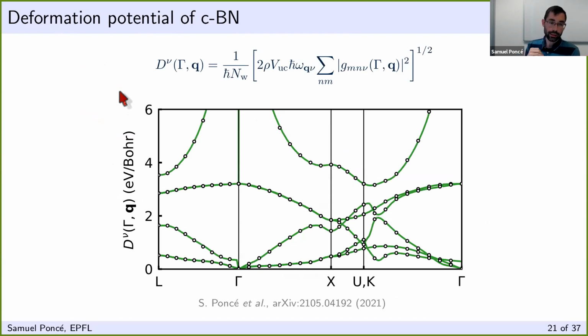So now we can look at the electron-phonon matrix elements, or more precisely, we can look at the deformation potential, which is the matrix element multiplied by the phonon frequency. Here I'm showing the deformation potential of cubic boron nitride. I'm showing this at k equal to the gamma point along the q high-symmetry lines, and I'm showing that for all the phonon modes of cubic boron nitride. So you have 6 branches. You can see them here. This is the LO, TO, and then the acoustic modes.